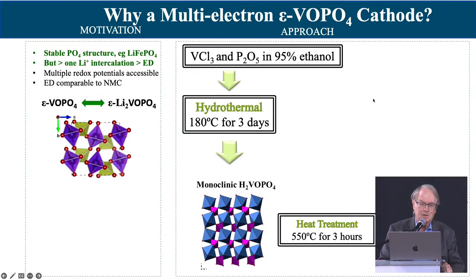So let's look at the alternative. I mentioned lithium iron phosphate is perfect for grid storage. It should be much lower cost. It has one major challenge, and if you have a Tesla car, read the instruction manual there. Lithium iron phosphate has a flat discharge plateau, exactly 3.5 volts. With all these other materials, you've got a nice slopey discharge, so you know exactly how much lithium you've got in there, how much you've taken out. So you've got your regular, if you like, gasoline gauge. With lithium iron phosphate, you don't know where you are. So the instruction manual says, when you get home, always plug it in.